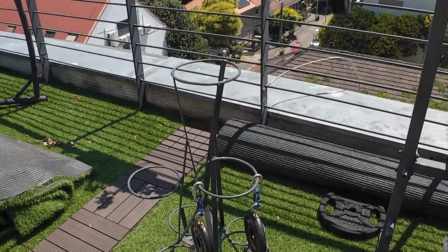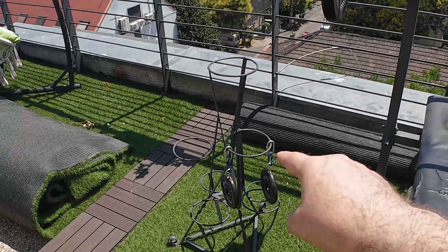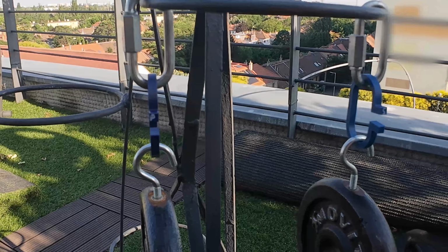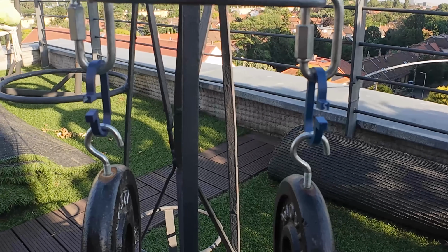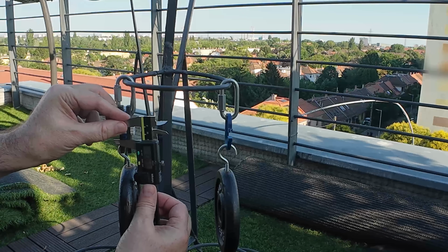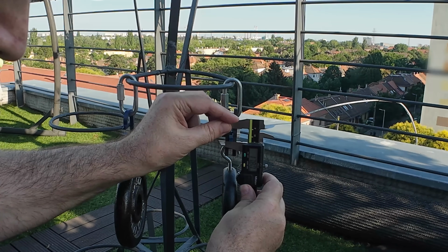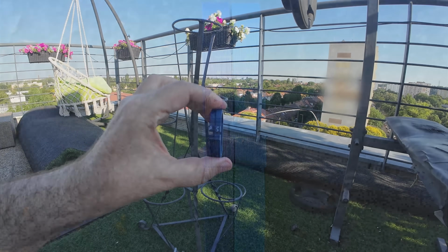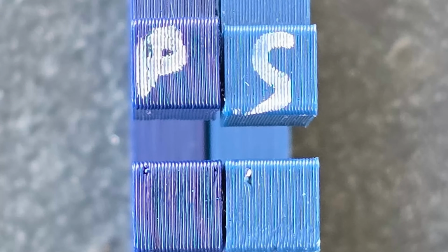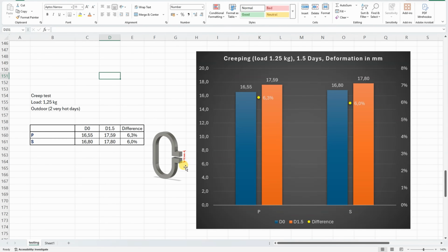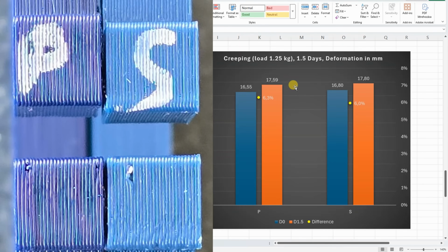This is day 2, almost 40 degrees Celsius outside, but I will measure them only in the evening. Quite a lot of deformation, but most of it happens in the first day for the ASA and ABS. 17.59. 17.80. But interesting, permanent deformation is smaller on the Stratasys. Blue is the initial deformation, distance between 2 reference surfaces, and orange after almost 2 days. And we can see a little bit more deformation on the Stratasys test object, but the creeping in percentage is almost equal. Additionally, after removing the objects, there is a little bit more permanent deformation on the object printed from Prusament ASA.